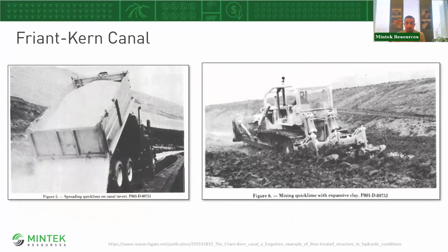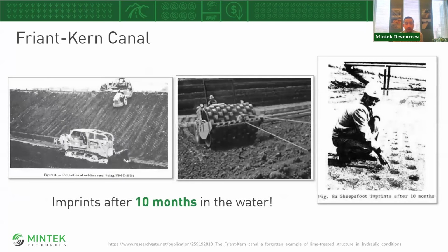So here we are in the process of how they did it. I thought these were kind of neat pictures. They moved material down to the canal bottom to spread the lime and do a little mixing, little quotes here, using disc harrows, fine for the time, great. We'll talk about equipment a little bit later, but still a pretty neat process. My favorite picture is here in the middle. They compacted using the world's biggest yo-yo, at least the biggest one I've ever seen. And it turns out a dose of 4% quicklime reduced the PI from a 47 all the way down to a 12. So pretty impressive just on the modification side.